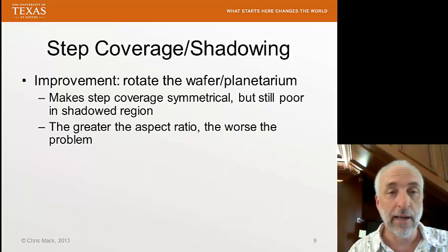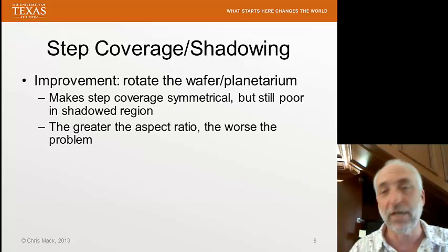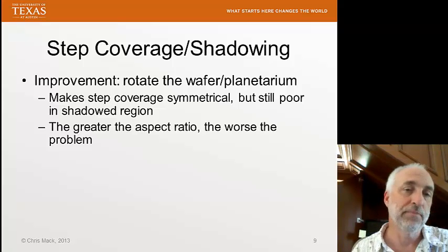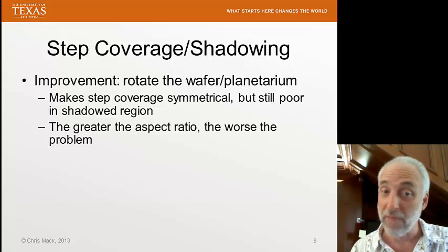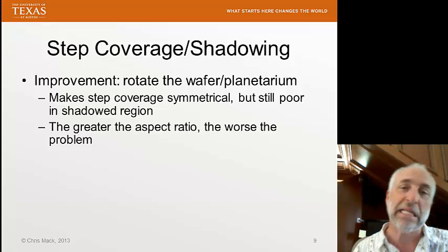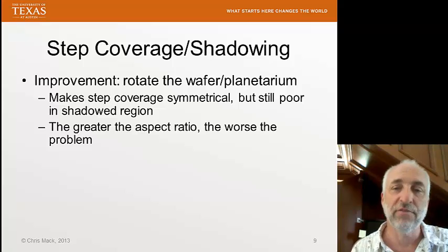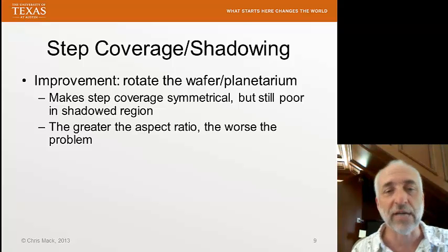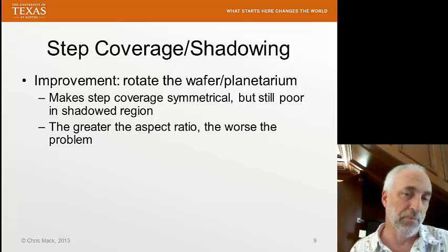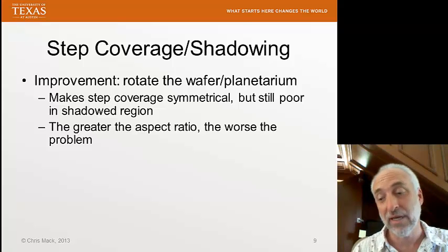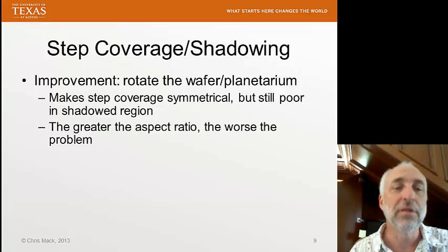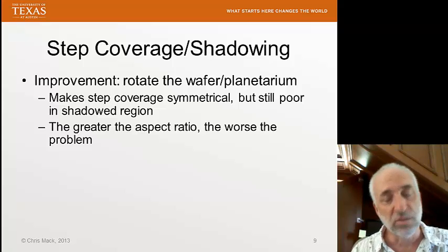Also, I can make the step coverage symmetrical. So the right and left side step coverage will be symmetrical. It may not be very good step coverage, but at least it will be the same. I'll still have poor thickness in the shadowed region, but again, it will be symmetrical. The greater the aspect ratio of the hole or the structure that is causing the shadow, the worse the problem is.